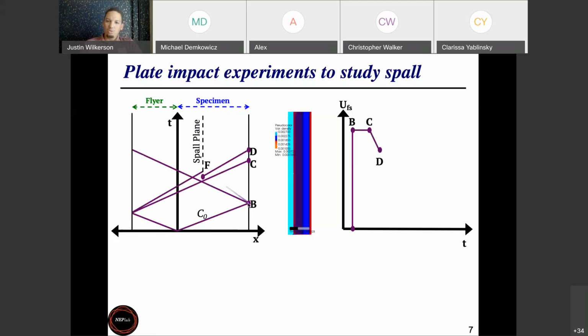After that, I hold in a Hugoniot state for a little while. So I jump up to some velocity and the back face just moves at that constant velocity. And it will hold at that velocity until another wave interaction comes. So from point B to point C, nothing interesting will happen. The free surface velocity will just be fixed at some value. What happens at point C is the first wave interaction is arriving.